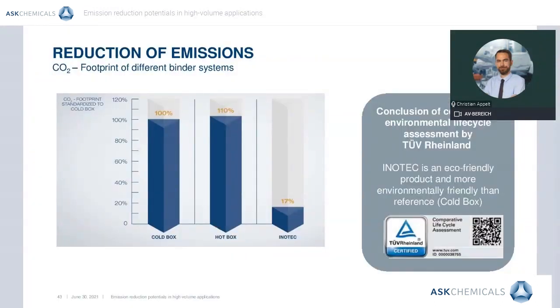The figure here summarizes the comparison of CO2 equivalents for different binder systems in an automotive light metal foundry normalized to cold box for permanent die mold applications. The lack of dry ice usage in the cleaning process and the lack of energy consumption for air treatment systems in case of Inotec leads to a considerable decrease for the CO2 footprint for Inotec. Conventional hotbox binder systems based on organic components show an even higher CO2 footprint than cold box.